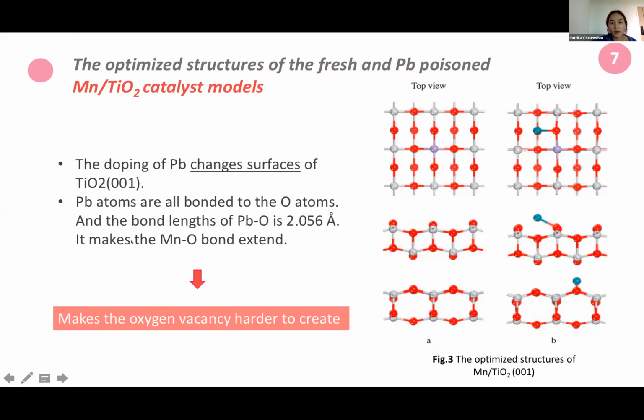Pb atoms are all bound to the oxygen atom, and the bond length of lead-oxygen is 2.056 angstrom. It makes the manganese-oxygen bond extend, and oxygen vacancy harder to create. It is well recognized that oxygen vacancy is favorable to the formation of chemisorbed oxygen on the catalyst surface and promotes the SCR